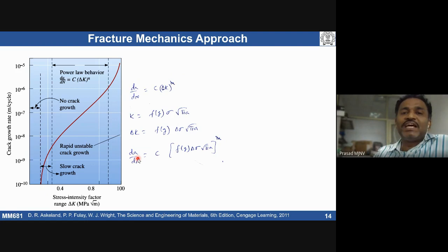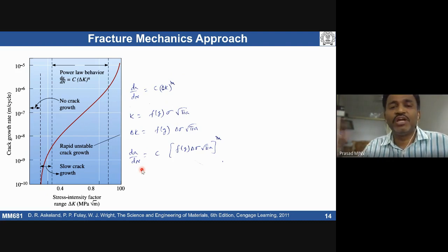For example, initially the crack length is A0. It has been extended to some length A1. I want this much crack length. How many cycles are required? What do you do? See, I know the crack growth rate is given by Paris law. You just assume that it's in the power law regime, regime 2. Now I want to know how many cycles are required for the crack to propagate from A0 to A1, or A1 to A2. What should I do?